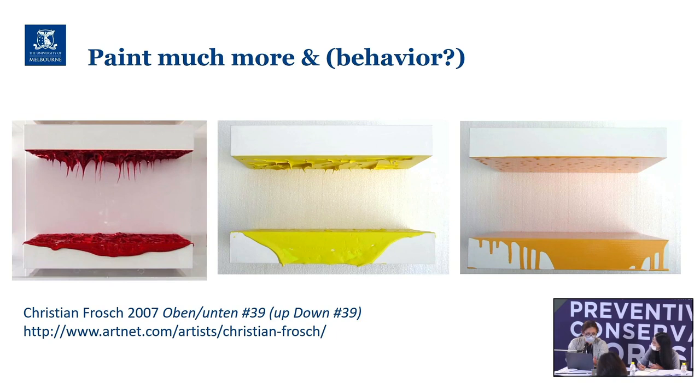Now, a big difference between your artist's paint and your latex is that this one is very thick, very buttery, and that is basically because of the high pigment load and also inclusion of things like fillers, calcium carbonate.